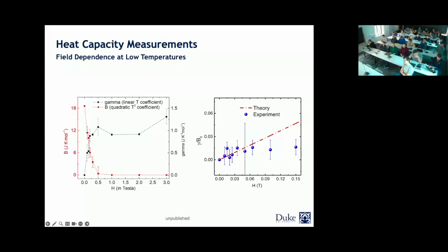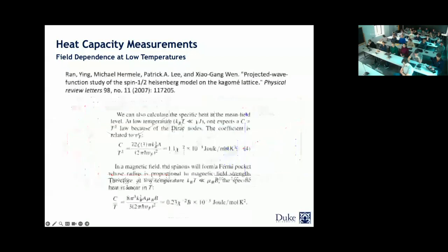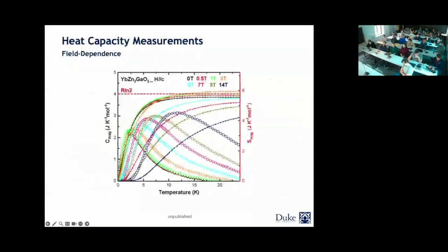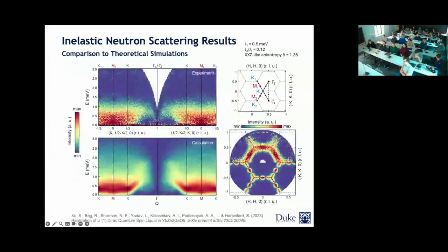What we also did, which I don't have in here, was look at the Fermi velocity for the spinons. Indeed, what we get is 75 meters per second, which is significantly lower than what you would expect for a very dynamic ground state. That could be the reason that, in this plot, the lower velocity of the spinons could be an indication that we are also missing this value that is shooting up.